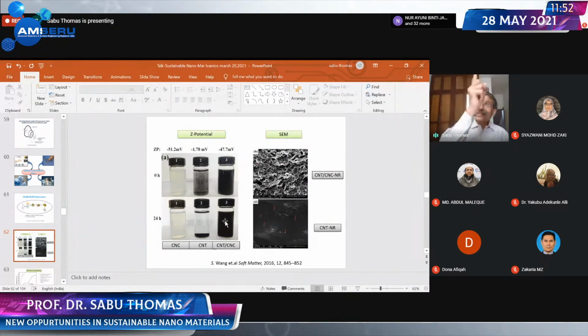The same thing you get when you mix this combination in natural rubber. CNT and nanocellulose together in natural rubber: excellent dispersion. Otherwise, CNT cannot be dispersed in rubber because CNT forms bundles. If you use CNT alone, you see lots of bundling of CNT in natural rubber.